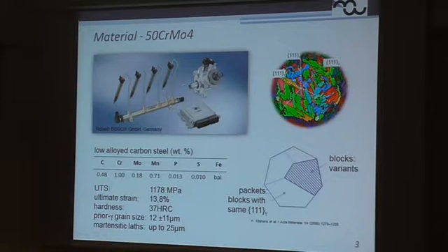So the material we are investigating is low alloy carbon steel. The German designation is 50 chromium molybdenum 4, and typically this kind of material is quenched and tempered, and so is our material, to a medium hardness of 37 Rockwell, which gives an ultimate tensile strength of 1178 megapascal and an ultimate strain of nearly 14%.